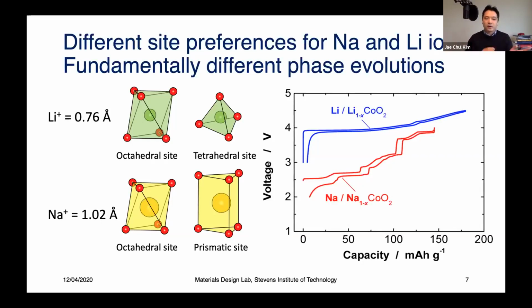So again, upon charging means removing sodium, and discharging means inserting sodium back. You see here the figure on the right, it's a voltage versus capacity plot. Capacity, if you see this unit, is charge per mass, the amount of charge you store in the battery. Comparing lithium and sodium, first you see that lithium-ion battery material has higher operating voltage and a much smoother voltage curve as a function of capacity compared to sodium.